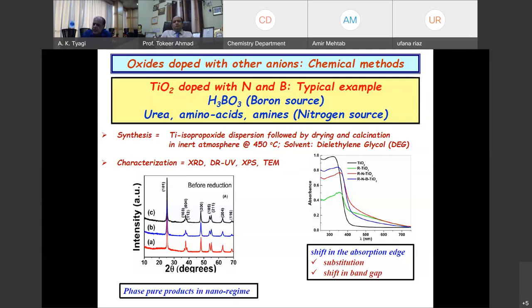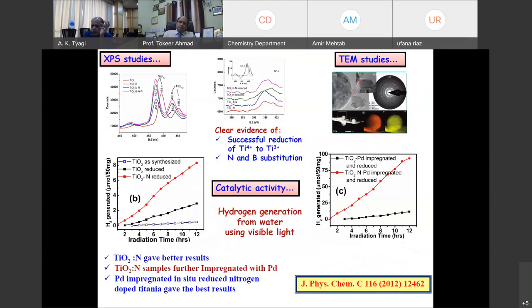Oxide can be anything. In this case, I selected TiO2 because TiO2 is a very nice material in terms of photocatalysis. You can see there is a red shift in absorption. So TiO2 band gap is here and then band gap is lowered considerably. So results are here. We used it for water splitting. TiO2 as synthesized was not so good. You partially reduce, you get better activity. You incorporate nitrogen, you still get better activity. And in nitrogen doped TiO2, you impregnate palladium, you have considerable enhancement in the yield of hydrogen by water splitting.